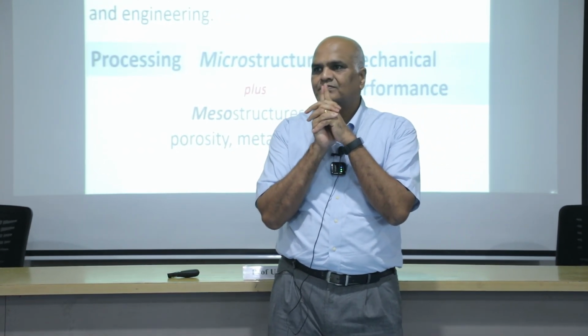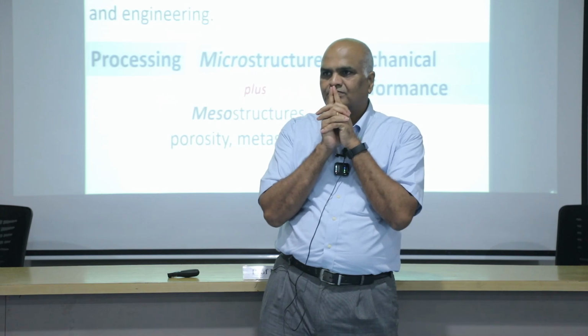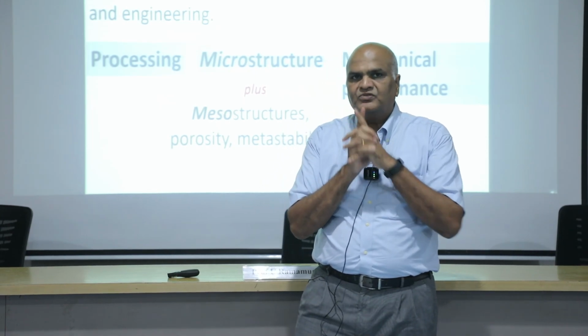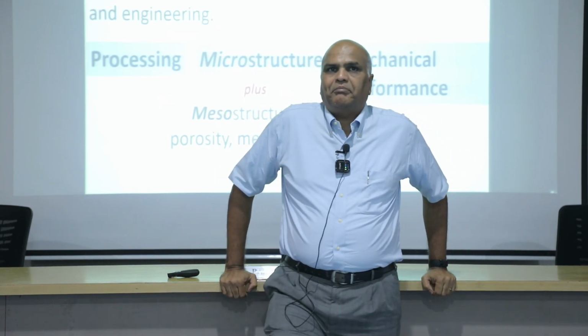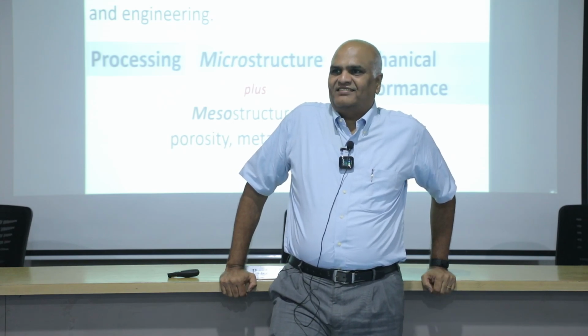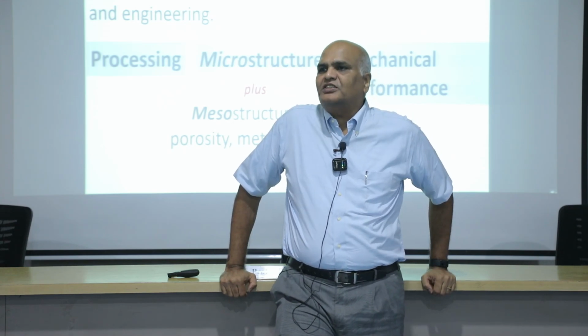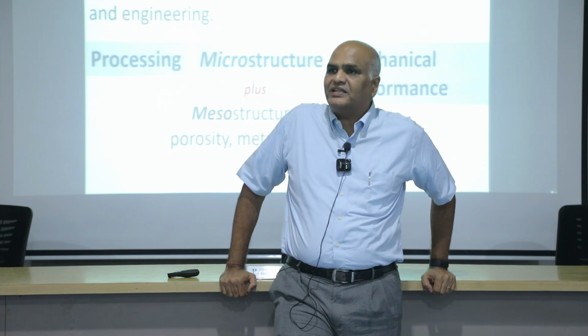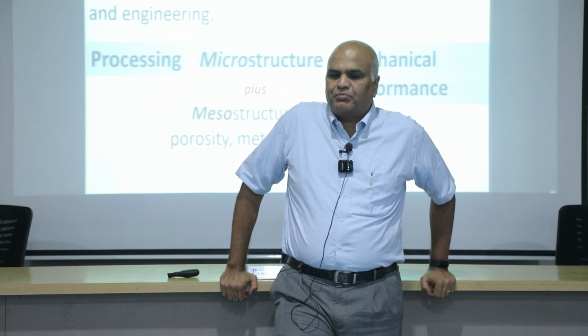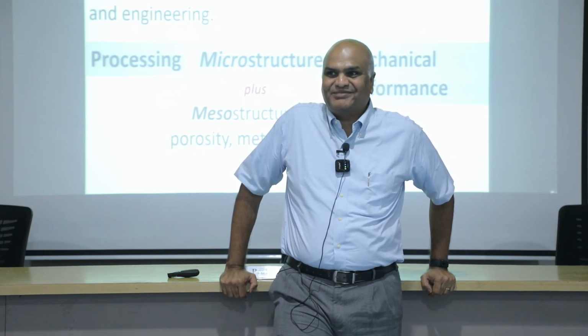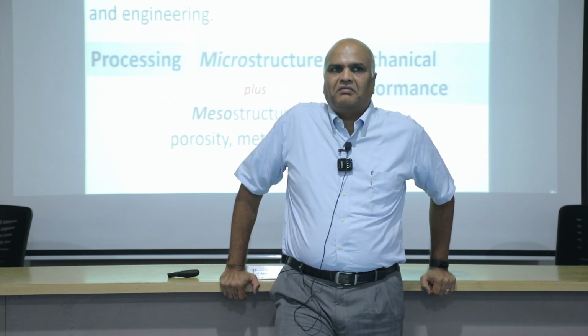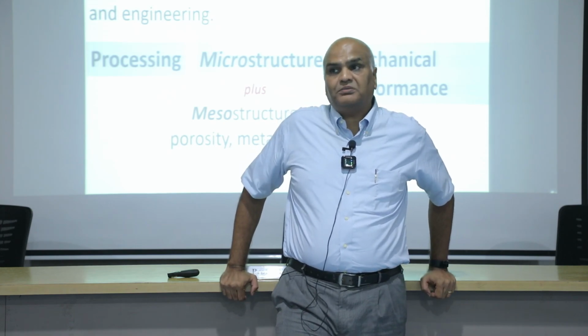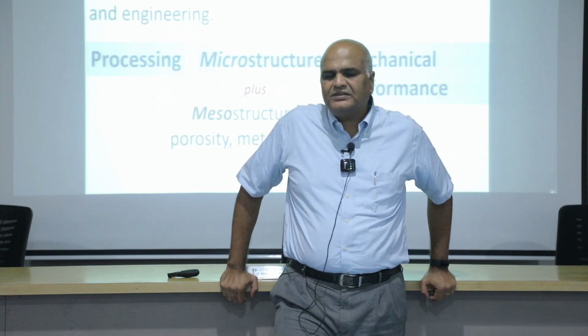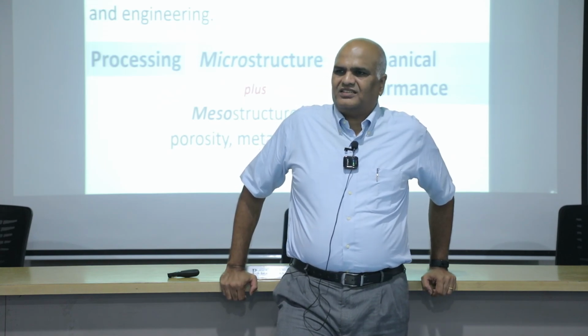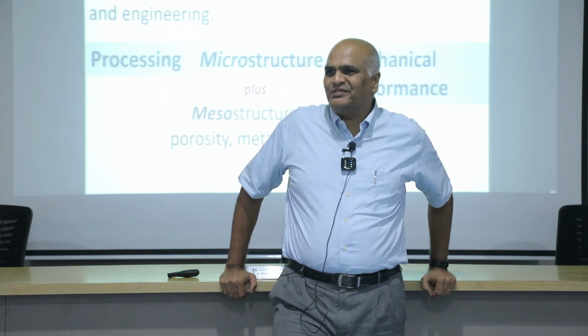Given the same parameters in the same process, is porosity predictable? Is it consistent? It's consistent. Predictability has not yet reached the stage where we can really predict the porosity. Porosity is inevitable in these materials. We can minimize the porosity but not completely eliminate it. Predictable, not there yet. If you can predict, then you can always find ways to eliminate it.